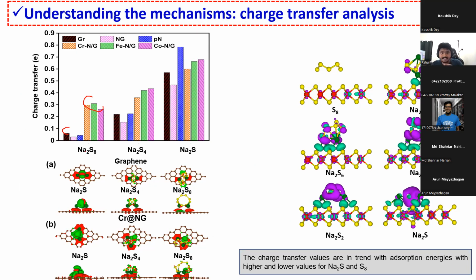Now this is nothing but the charge density difference profile, where we can find where the charge is accumulated and where the charge is depleted. To find that, we did this analysis, and the red color indicates the charge accumulation and the green color indicates charge depletion. From this you can see that the charge is basically accumulated at the interface between the substrate and the polysulfide, and the charge is depleted from the polysulfide itself.